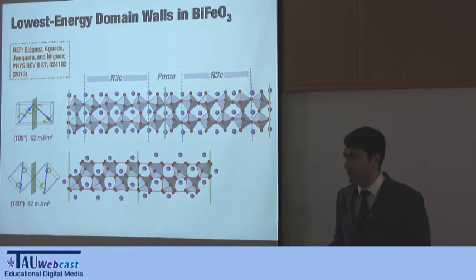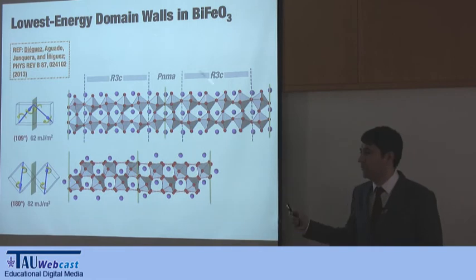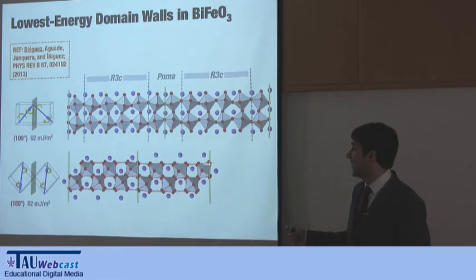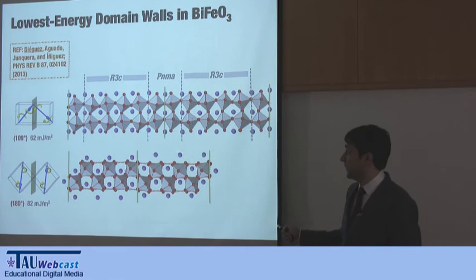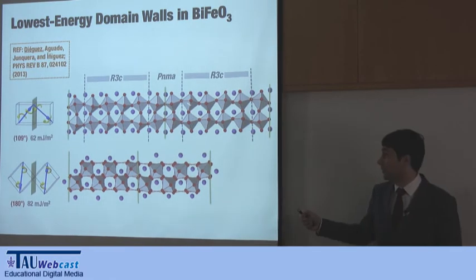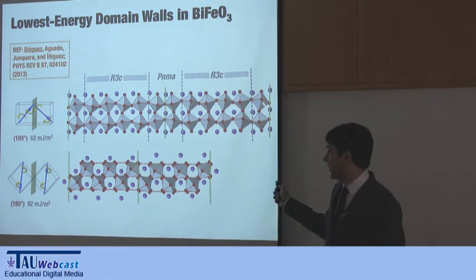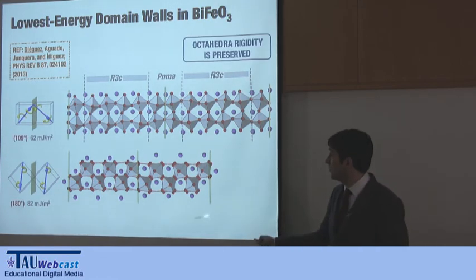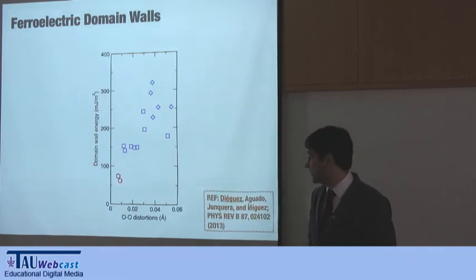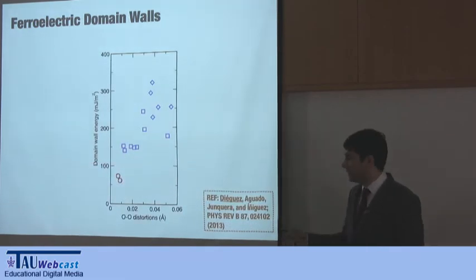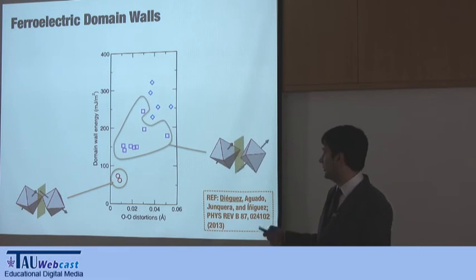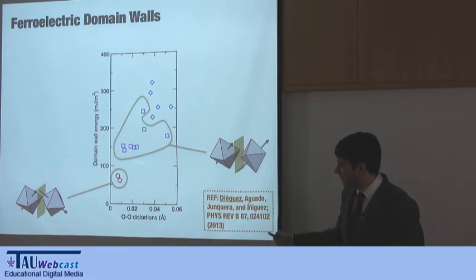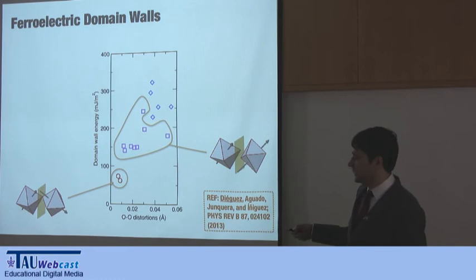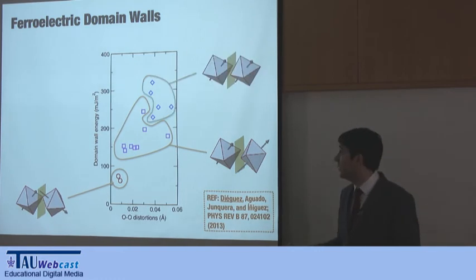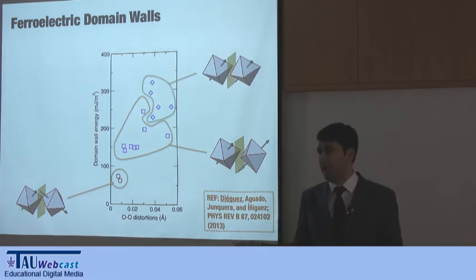Another thing, if you are familiar with domain walls in magnetic materials, is that in ferroelectrics they are very, very sharp. So it's like 2 unit cells. This is what happens with pure ferroelectric materials. The same is true here. There is very little octahedral distortion, and you can go on quantifying this argument, although I'm going to very briefly just say that it's all reduced to a matter of how unhappy the octahedra are, basically.